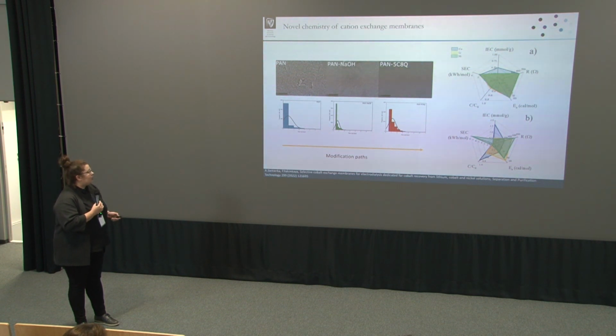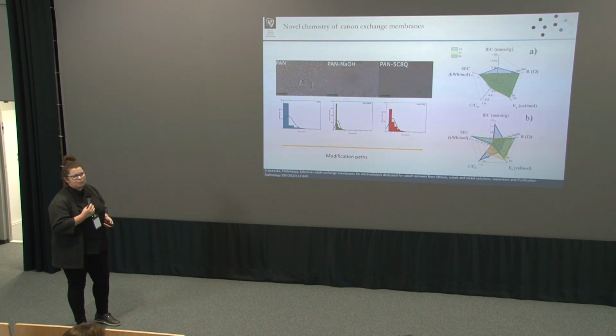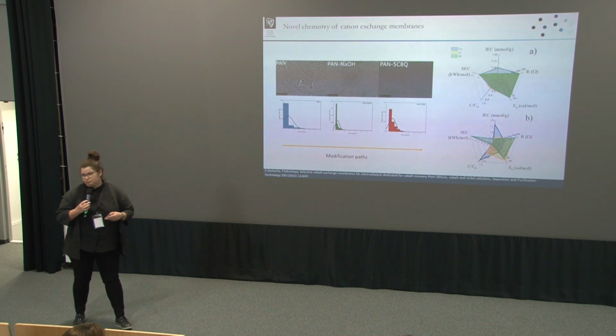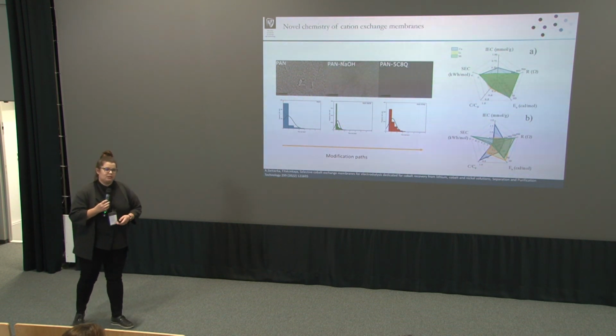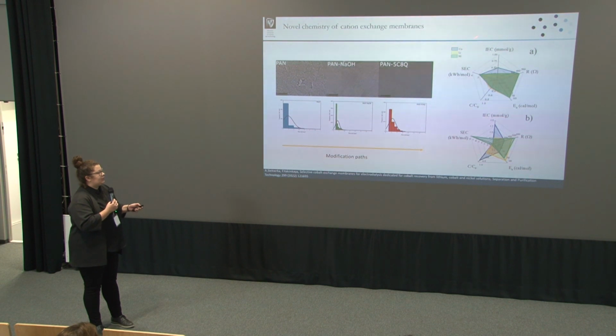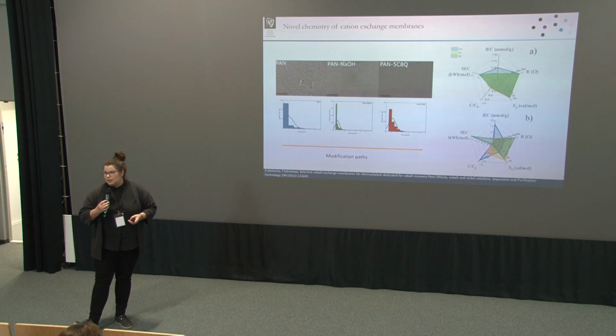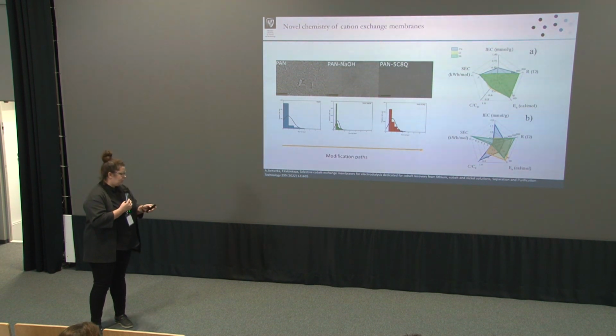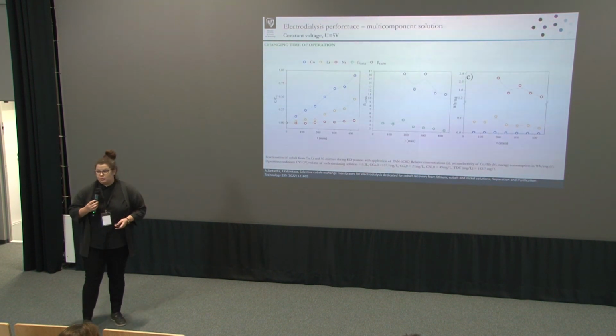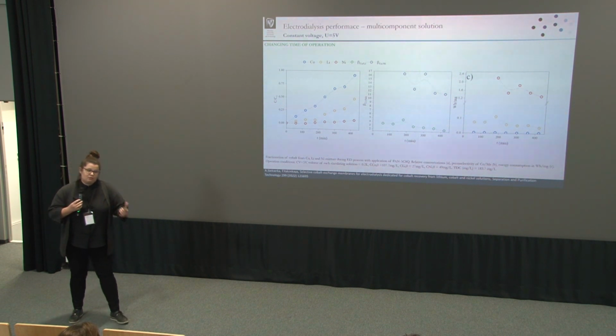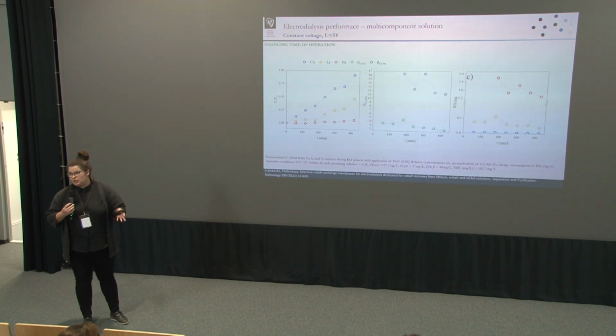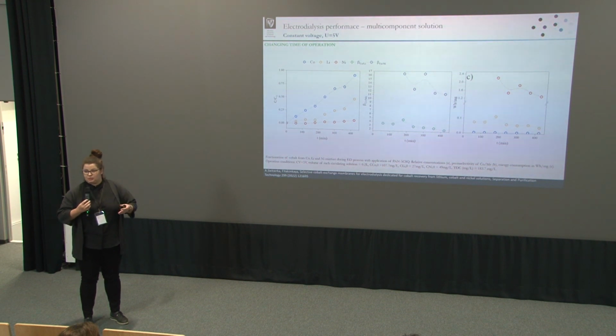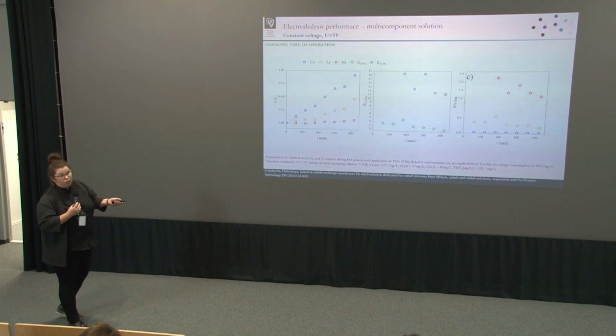This is how the membranes look. It's a very stable membrane without any hole defects, so it's fine. The properties strongly depend on the cations that touch the membrane. But what's going on during the process? I checked, obviously, time, voltage, and TDS of the initial concentration of all elements.